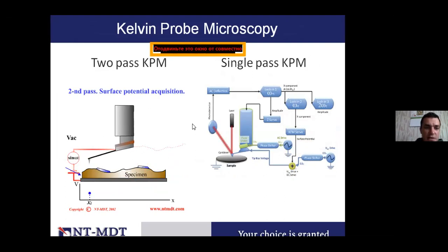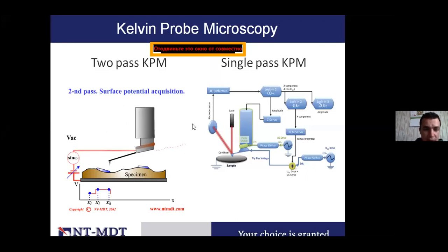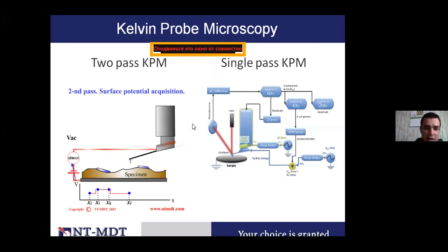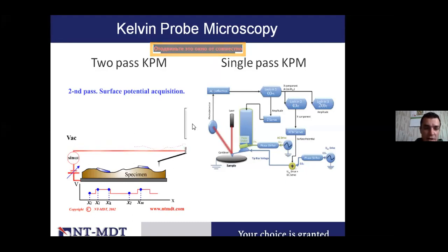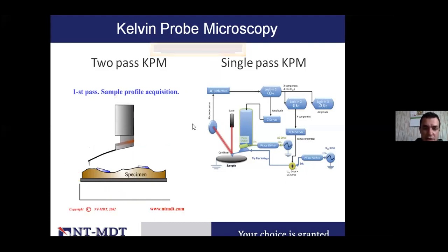At some distance, we apply DC voltage and AC voltage. And according to a special algorithm, we can measure the work function or surface potential of the particular area on the surface.